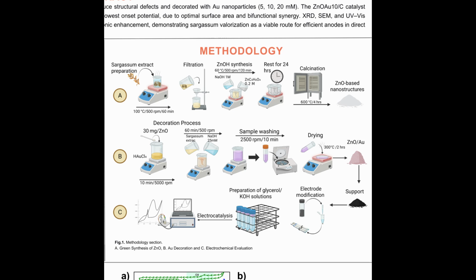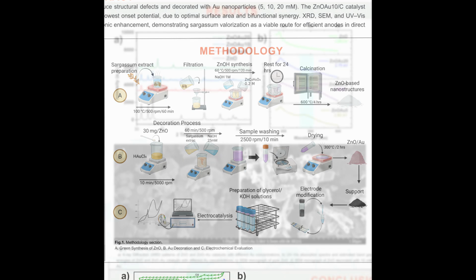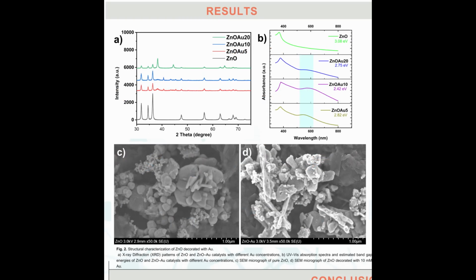Stage C: electrode preparation and electrochemical evaluation. The zinc oxide gold nanocomposites were dispersed and drop cast onto glassy carbon electrodes. Tests were performed in 1 molar potassium hydroxide with varying crude glycerol concentrations. Results and discussion. Structural characterization. X-ray diffraction confirmed the hexagonal wurtzite phase of zinc oxide in all samples with no secondary phases. Metallic gold peaks became more intense as loading increased, confirming deposition without altering the zinc oxide lattice.